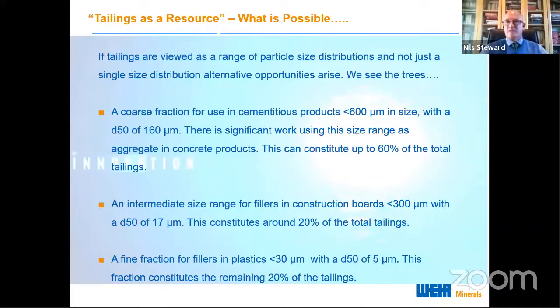If we have an intermediate size range, less than 300 microns, a D17 or 17, a D50 or 17 microns, that constitutes about 20% of the tailings, and is ideal for actually constructing construction boards out of it. Gypsum is not dissimilar to tailings in terms of the particle size distribution, and what we've managed to achieve with foam tailings is not dissimilar to what actually is achieved with gypsum board. So we're able to start saying, well, maybe we can actually manufacture a board out of foam tailings. It'll certainly have fire resistance. It'll certainly have the insulation capacities.